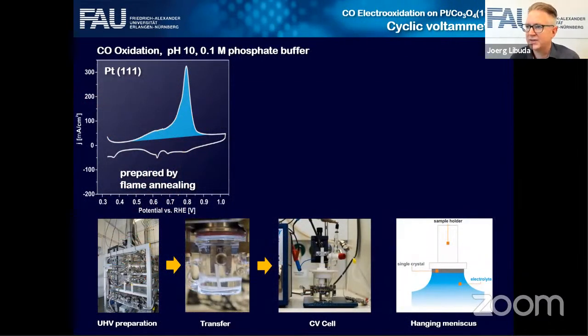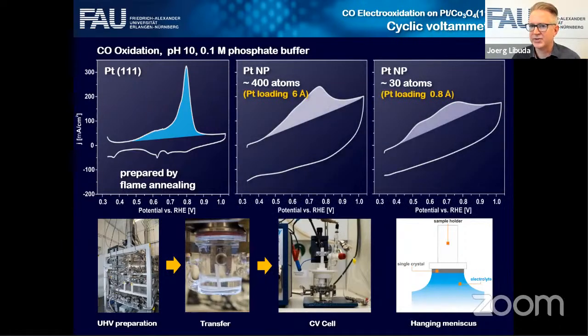So you can do CO oxidation, a simple test reaction. That's CO oxidation on a platinum 111 surface at pH 10 here. And if you do the same experiment on these model surfaces, you see that the cyclic voltammograms look very different. So this pre-peak at low potential is much stronger. Yeah, and that tells you that there's a lot of oxidation without poisoning of the surface by CO. Yeah, and that's mainly because on such a surface that has small nanoparticles, you can provide OH groups to react with the CO via the interface and via the support. Yeah, and that allows you to do the CO oxidation already under conditions where the surface is poisoned on a single crystal surface.